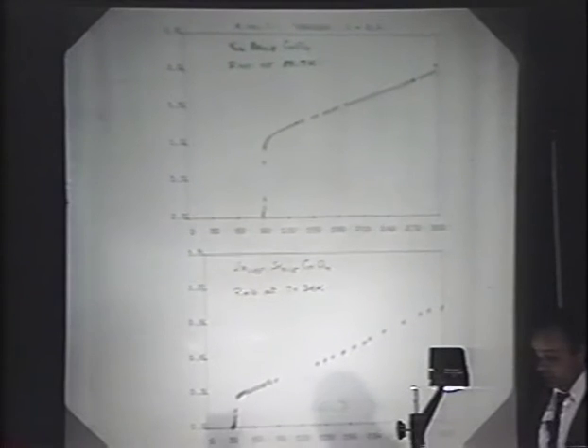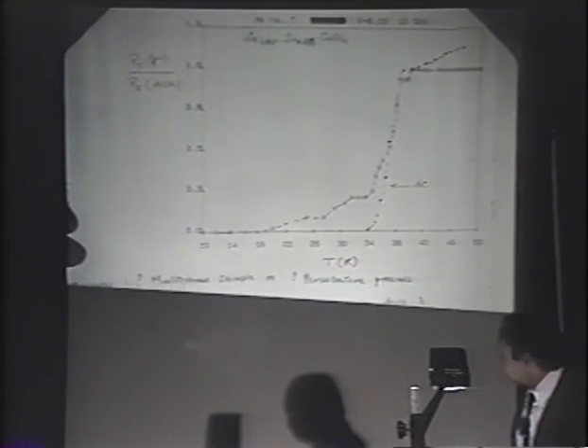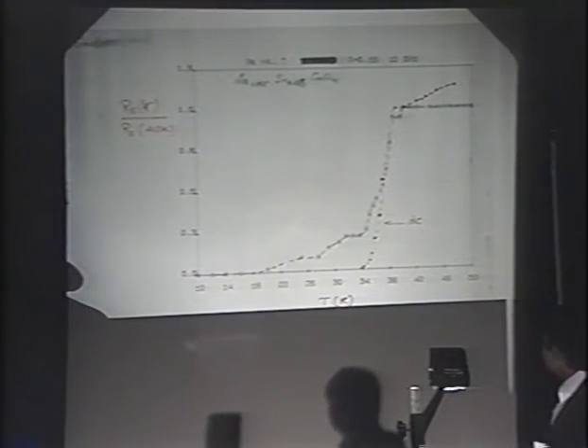Just for the record, we make our own samples, and they appear to be pretty good. We have also measured the susceptibility, and we see pretty much what other people see, Curie-like behavior at high temperatures, and also the diamagnetism. Let me show you some measurements at 10 gigahertz on the surface resistance of lanthanum strontium copper oxide. I've normalized the data to 40 Kelvin.